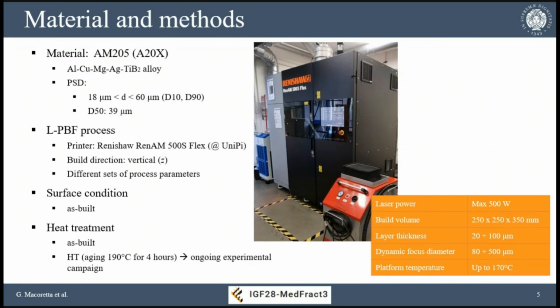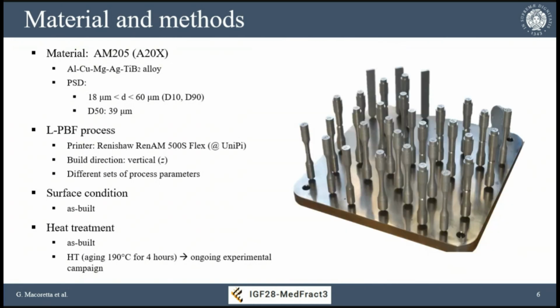We investigated different sets of process parameters, so here you can see an example. Surface condition was only as-built, so samples were not machined, because we want to study the effect of surface roughness on the fatigue performance of our material.